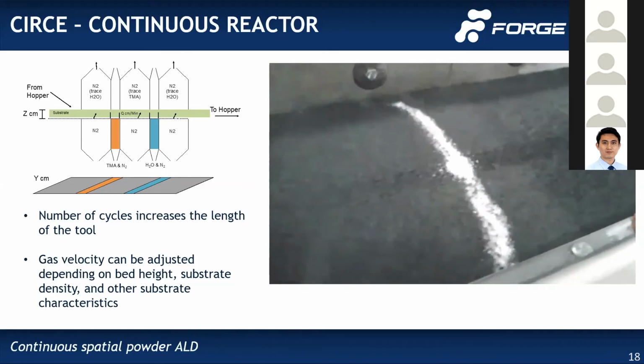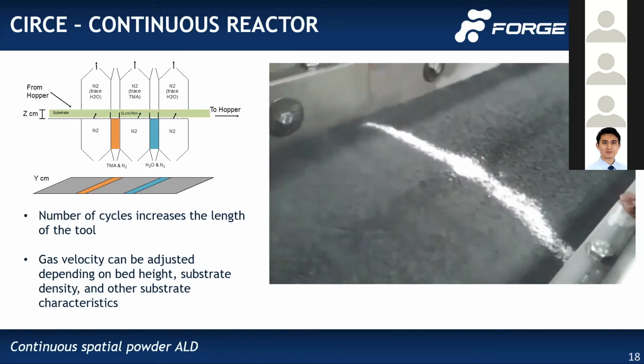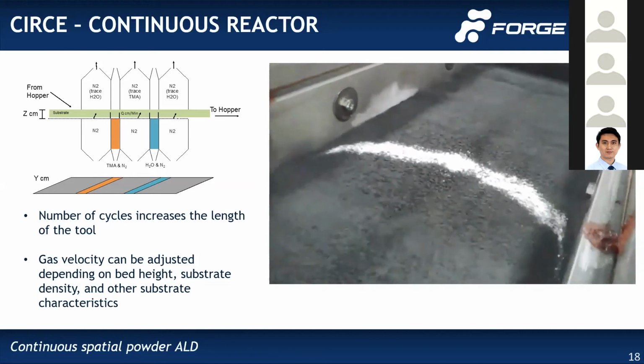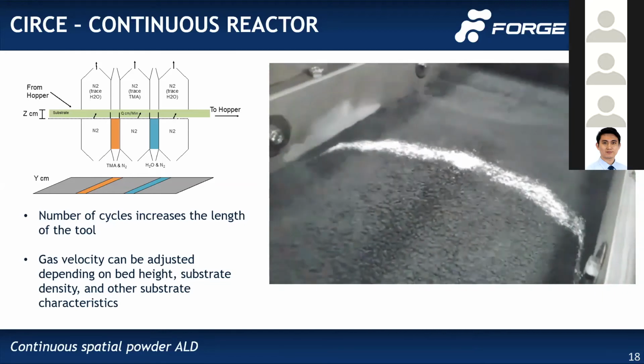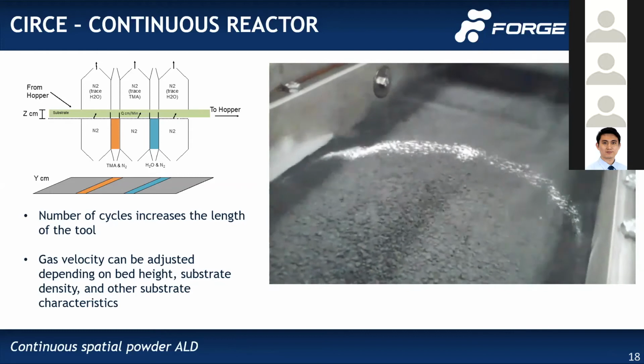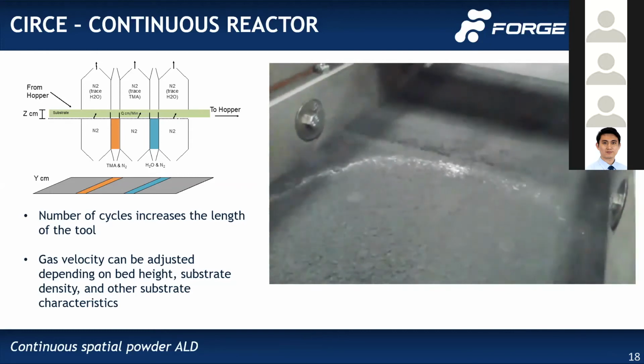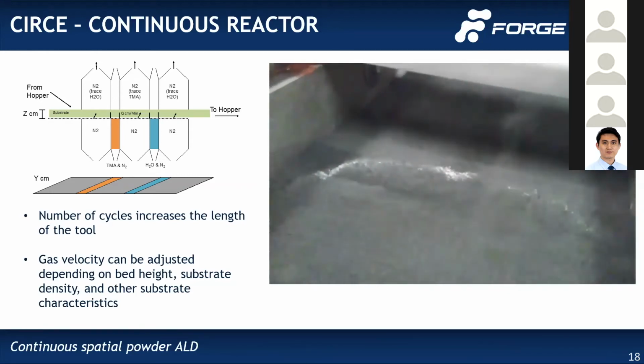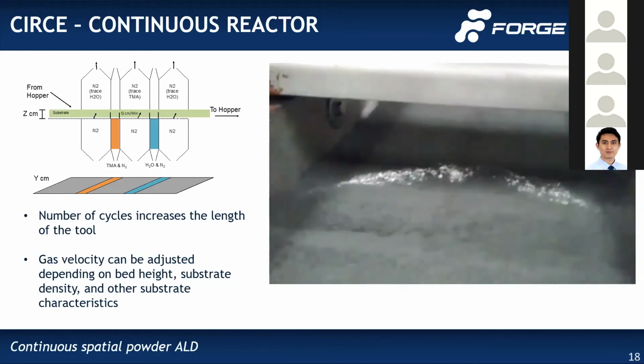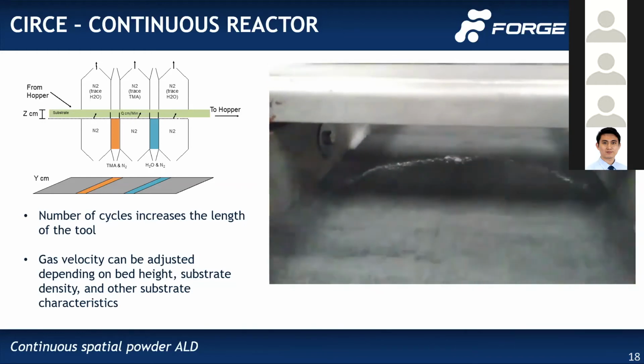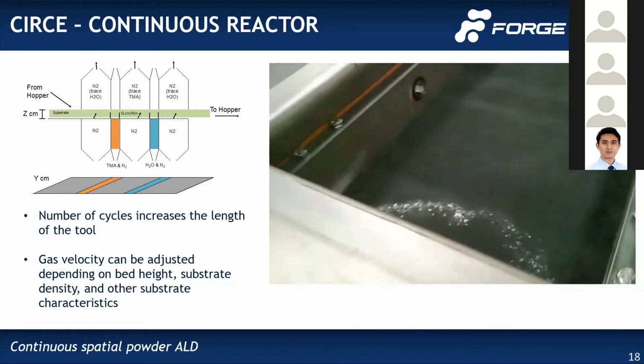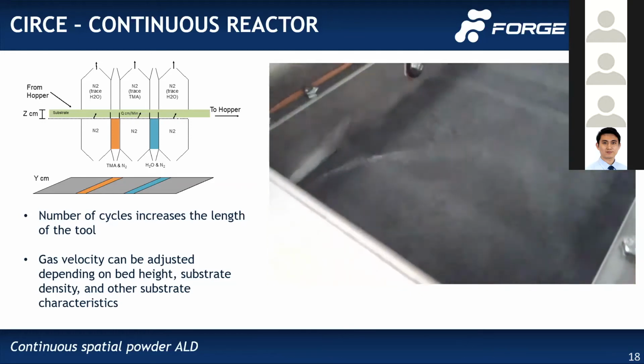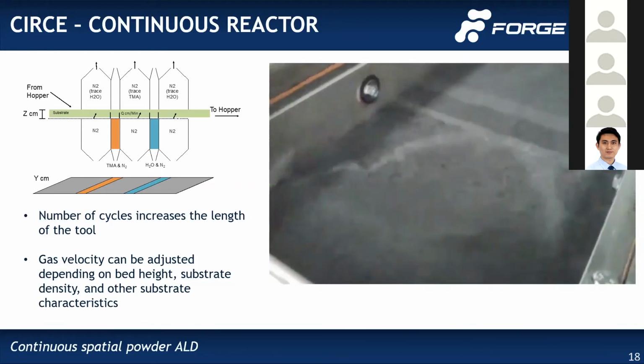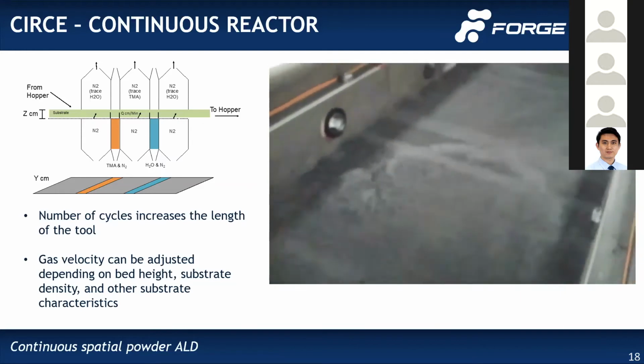So on this continuous vibrating bed, the powder moves along and it goes through those different zones right there. It's going through an exposure zone to the different precursors. And again, this is like an aluminum oxide deposition, so you have trimethyl aluminum and water. That powder just moves along and goes through about 3 different cycles, and it gets to the end of the system, and then that powder is collected.